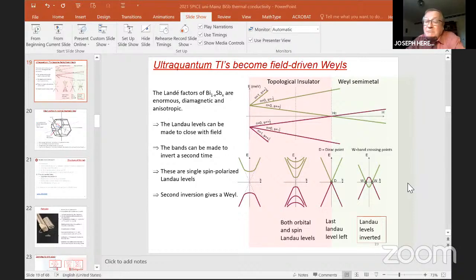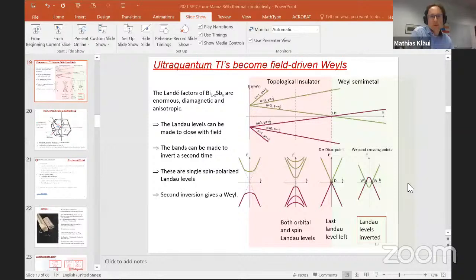The charge carrier density primarily comes from the purity of the starting material. So the question is, how good bismuth and how good antimony can you buy on the market? You can buy 6 nines, but with commercial material, you can get the charge carrier density not below 10^17 by freezing it out. So in reality, we zone refine the material in-house before we use it for growing crystals, and it's the only way to get to 10^15. The best commercial stuff will give you 10^17. So you have to make in-house purifying for the materials to get to that low number, because it is quite low. Oh, absolutely. Absolutely.